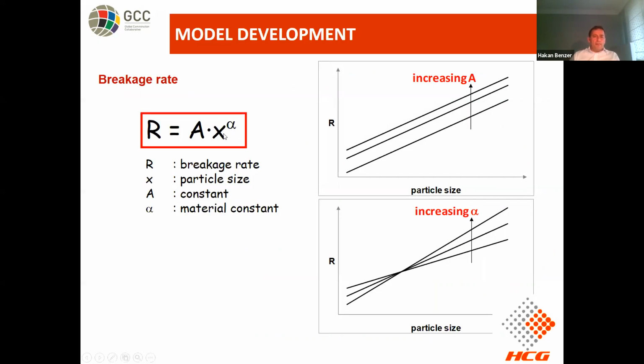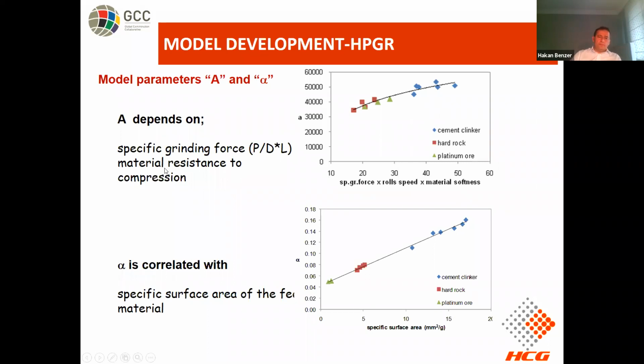Rate varies with particle size with constants A and alpha. A depends on specific grinding force, which represents the geometrical condition and also the operational pressure value. And also we have a material softness or material index, which I'm going to define later. And also we needed to define the feed size distribution going into the system, which is defined by alpha. And we address this with the specific surface area.